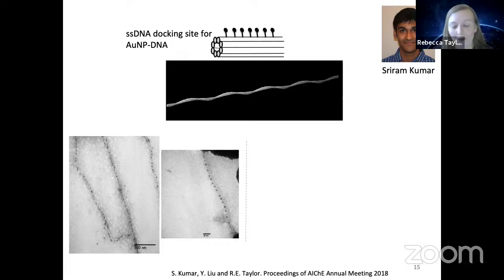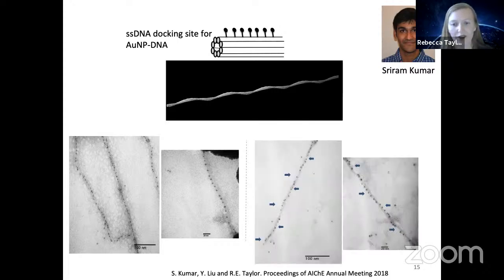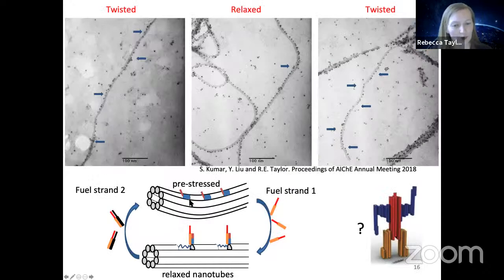So here on the left, you see we can make a DNA nanotube and we can decorate it with gold nanoparticles, distributed along its length. The scale bars here are 100 nanometers and 20 nanometers, in case you can't see them. Okay, we can also make structures that are twisted. And the evidence of twisting is that you see those little gold nanoparticles switching sides. So they go from staying on one side to switching sides. And what we decided was that if we build pre-stressed systems, we could then use a strand displacement reaction to release that stress. So you could imagine that you could form a twisted tube, like a helical tube, and then pull off all these regions that are applying the pre-stress and allow the tube to relax. And so here we actually have a demonstration of the fact that we can switch back and forth. With the same batch of tubes, depending on which fuel strands we introduce, we can twist and untwist.